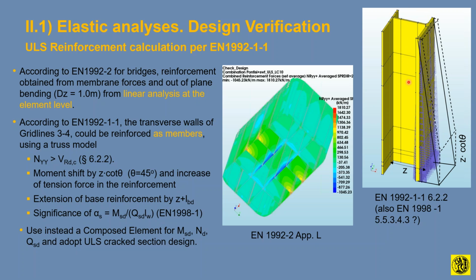With an 8-meter part and then 2 flanges. In this case, we can calculate the shear, bending and axial force using Diana through a composed element, in fact, figure out the forces. And then if these forces here, or even from the elastic analysis, exceed the cracking under bending and shear force of the particular element of the center part of this beam here, then we should use the truss analogy and reinforce this particular wall for the entire shear forces generated as a cantilever using horizontal reinforcement, assuming a truss analog.